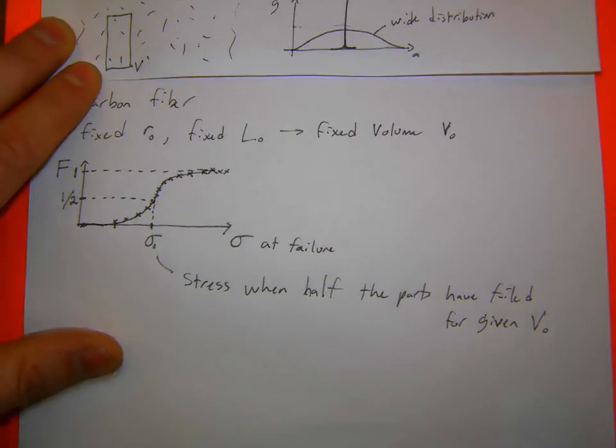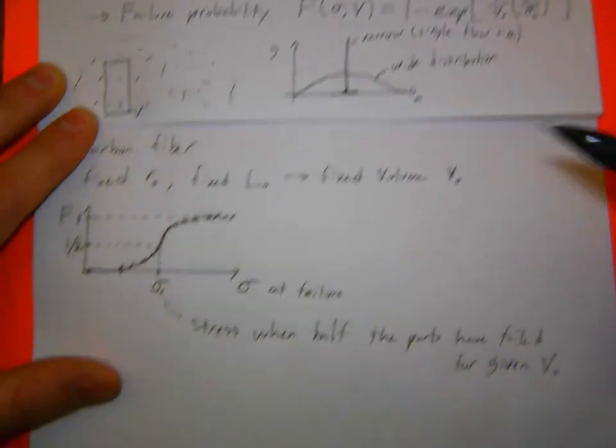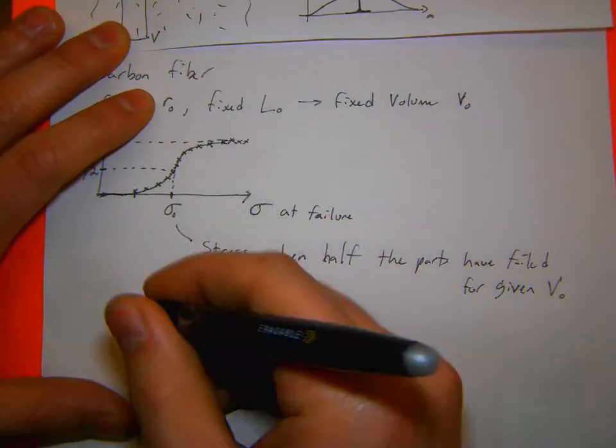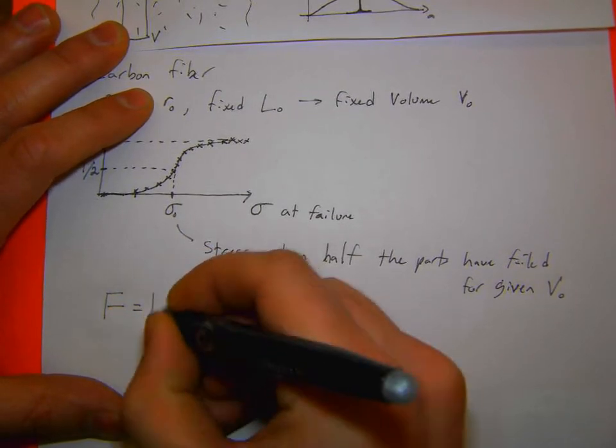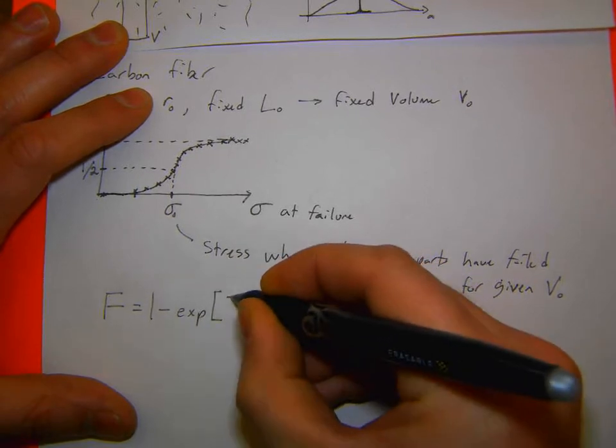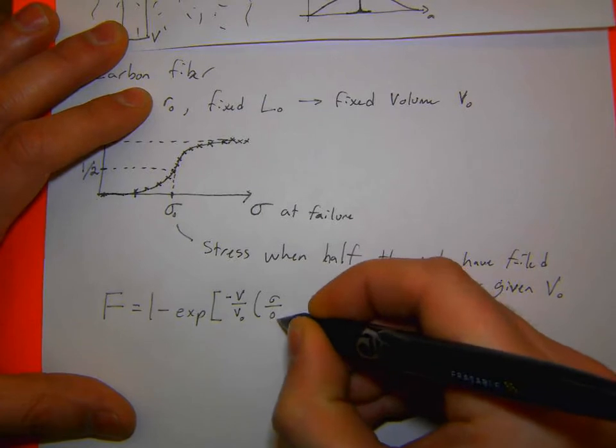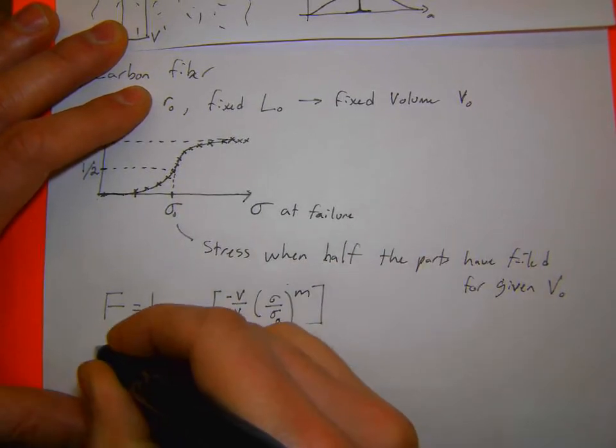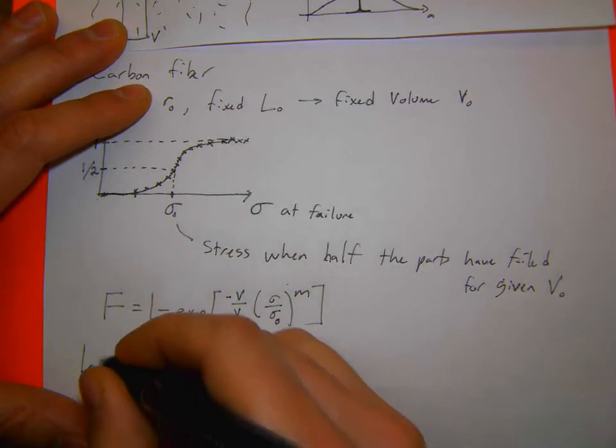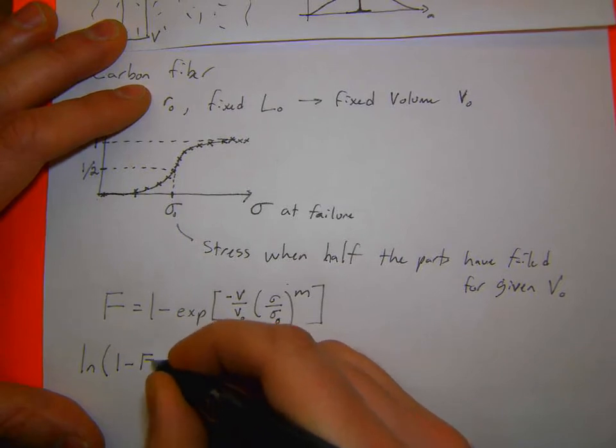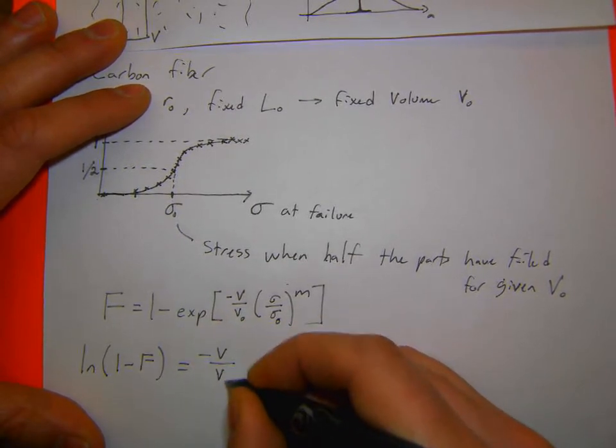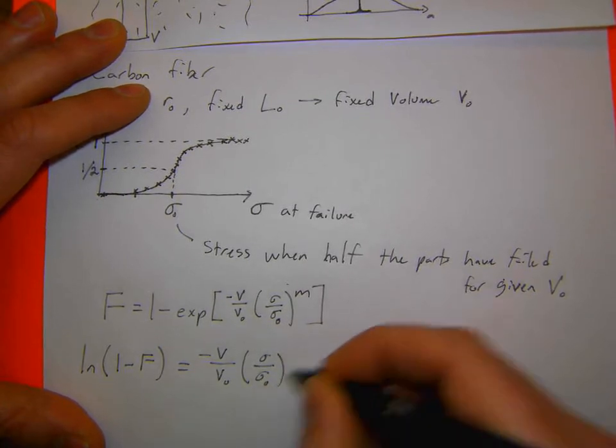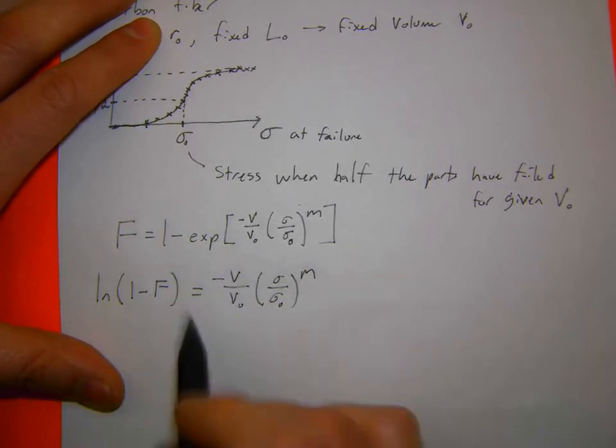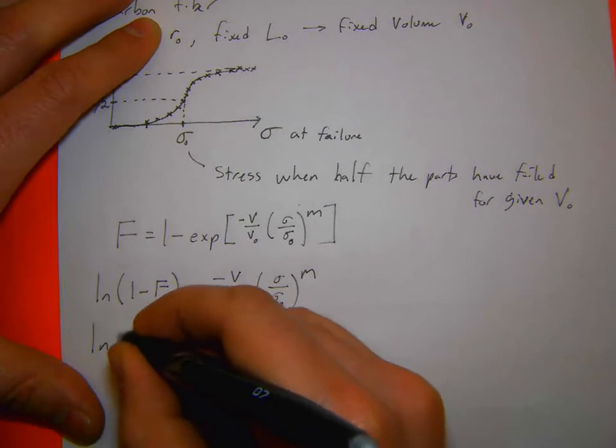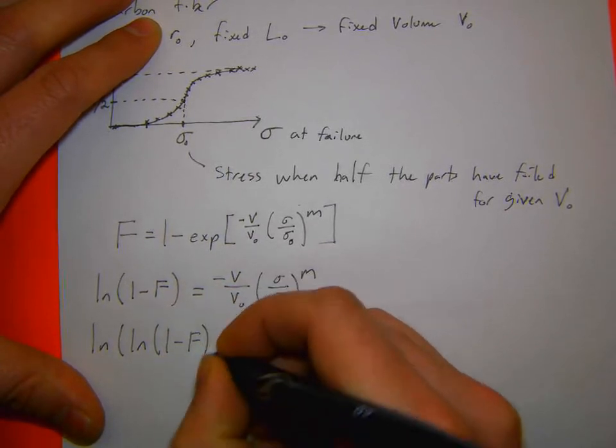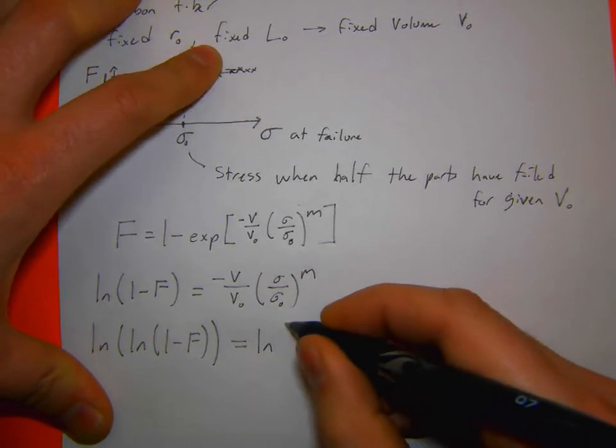So I'm going to show you now a reorganization of this equation, and this is how it's often plotted out. I'm going to take that F is 1 minus exp of minus V over V naught, sigma over sigma naught to the M. I'm going to say this is the natural log of 1 minus F is equal to minus V over V naught, sigma over sigma naught to the M. And then I'm going to take another log, so I've moved stuff around. I'm going to take another log, natural log of natural log of 1 minus F is equal to, now, natural log of V over V naught.